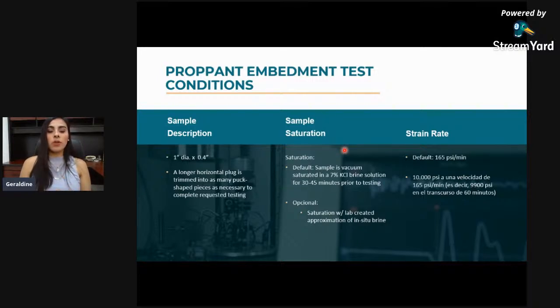Saturation. Here, the standard is to saturate the sample with KCl at 7% for 30 or 45 minutes prior to the testing. Optionally, we can create any brine at the laboratory. The strain rate will be 165 psi per minute. Why this strain rate? Well, you want to apply a total axial load of, more or less, 10,000 psi. And you want to reach that axial load in a time of 1 hour or 60 minutes. So if you use that strain rate, this is the time where you will reach that axial load.